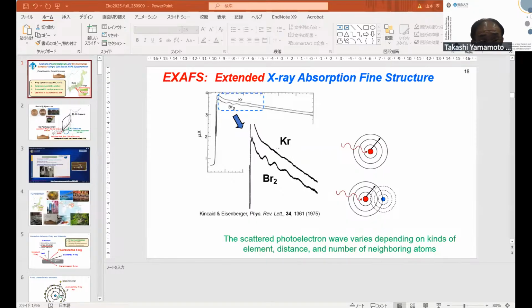Okay, I'll explain first about EXAFS, extended X-ray absorption fine structure. This is the spectra of krypton and bromine. Krypton is a single atom molecule, and bromine is a two-atom molecule. The difference is that with krypton there is no atom around, but with bromine molecules another bromine exists a few angstroms nearby. In the case of krypton, the emitted photoelectron wave goes away as it is.